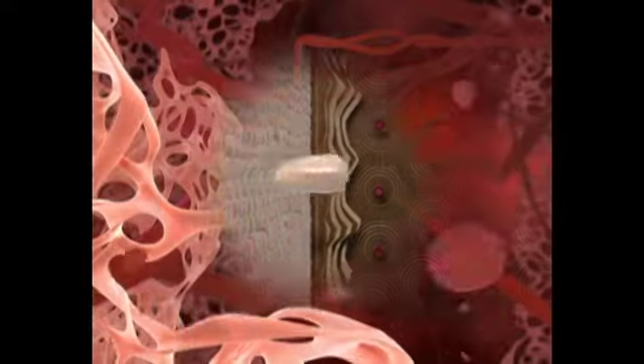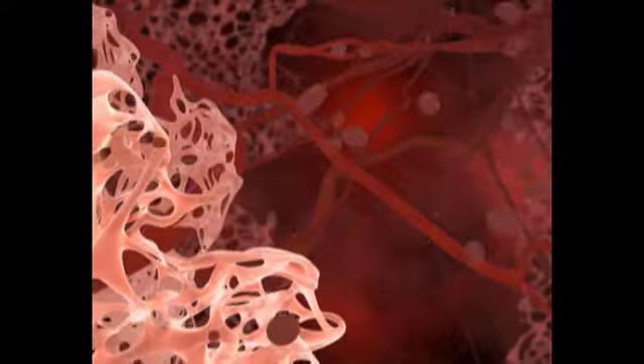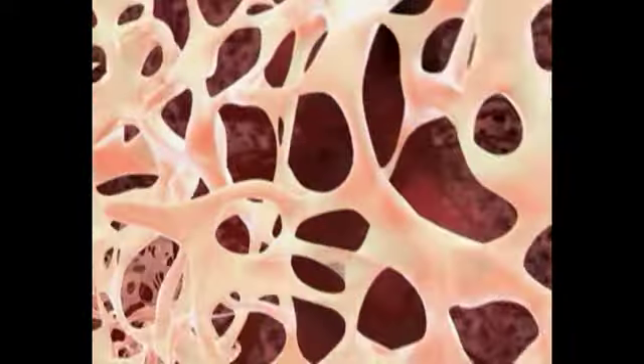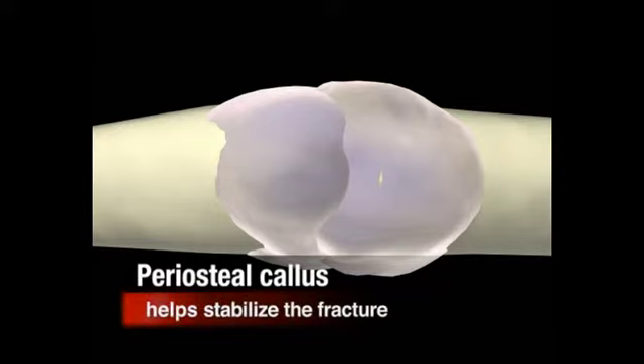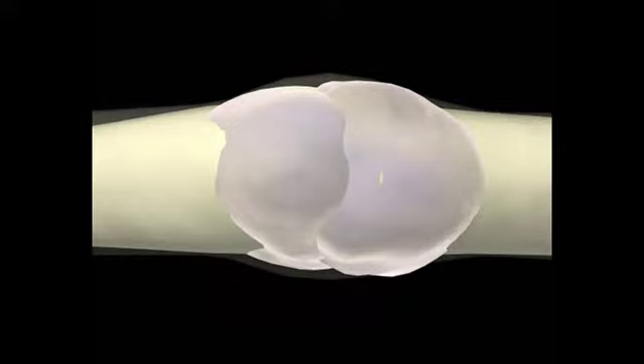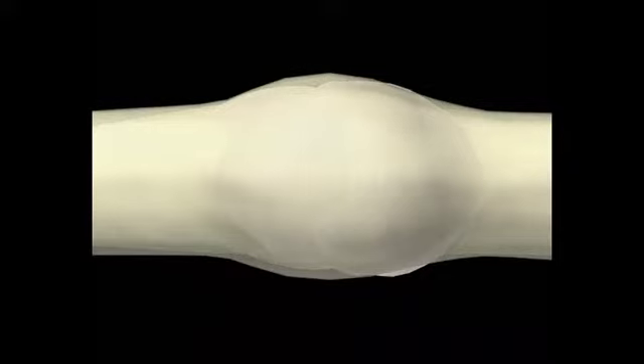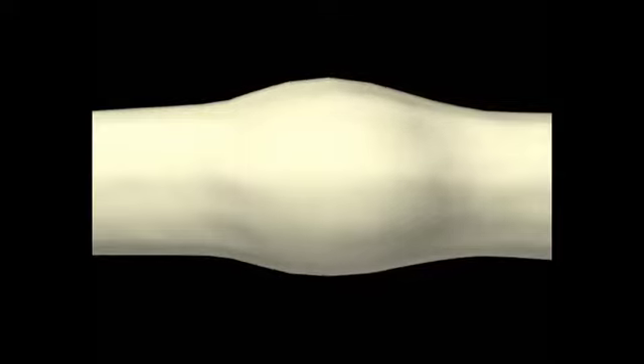Osteoblasts, probably from these membranes, proliferate in the granulation tissue. Within 3 weeks, a collar of woven bone, or primitive, unorganized bone, forms around the fracture gap, called the periosteal callus, which helps to stabilize the fracture, although some mobility remains. Within the next few weeks, the callus transforms into mature lamellar bone, which has increased organization. When this strong collar eventually completely stabilizes the region, the fracture is clinically united. After union, the excess callus disappears.